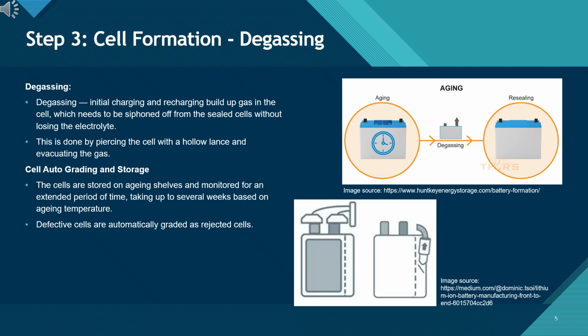However, during the initial charging and discharging cycles, gases inevitably form inside the cell. To prevent swelling or deformation, the degassing process is applied. This involves carefully piercing the cell with a hollow lance to evacuate the gas while ensuring that no electrolyte is lost. Once the gas is removed, the cells are resealed. This step ensures that the pouch or casing is fully secured, allowing the battery to maintain structural integrity and long-term performance. In short, aging verifies stability, degassing ensures safety and cell integrity, and resealing prepares the cells for their final stage before pack assembly.